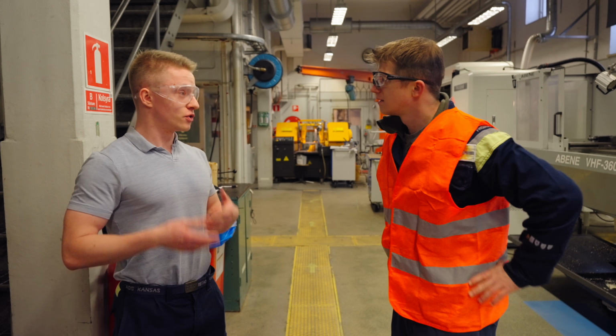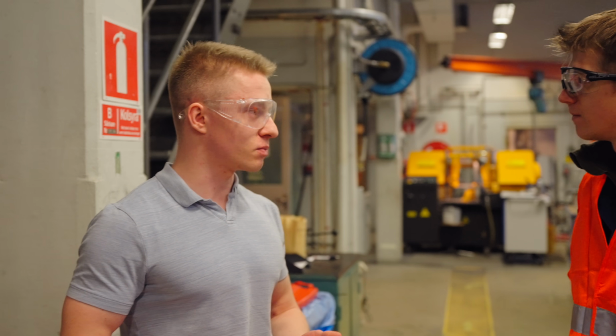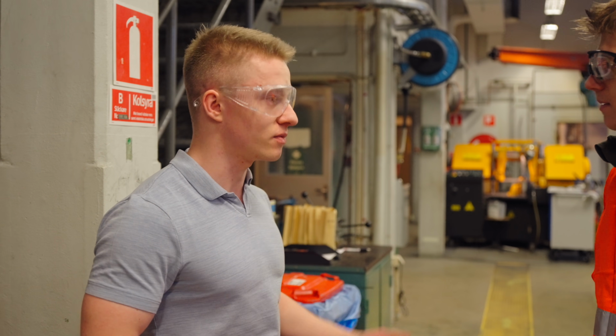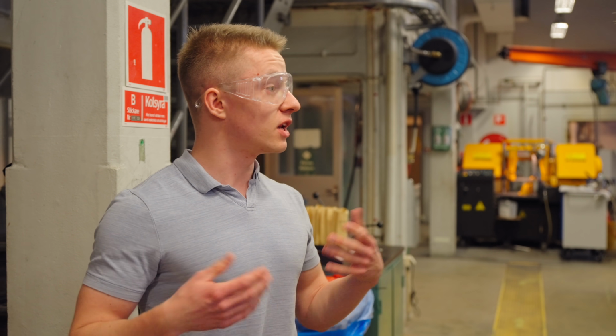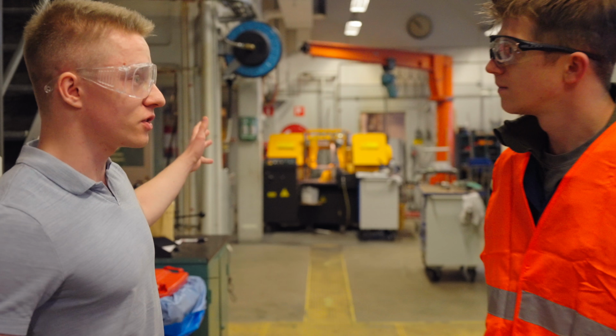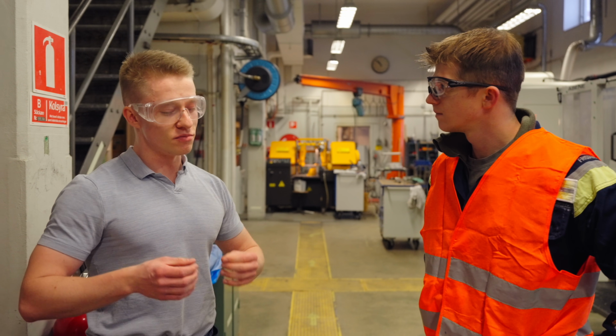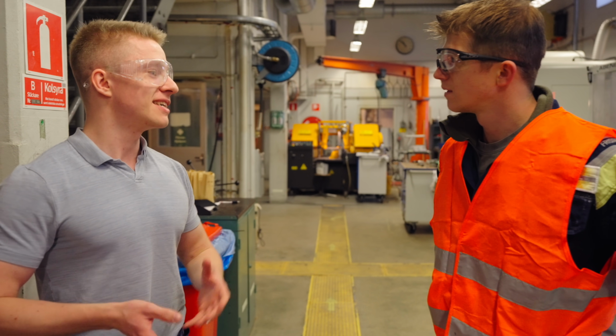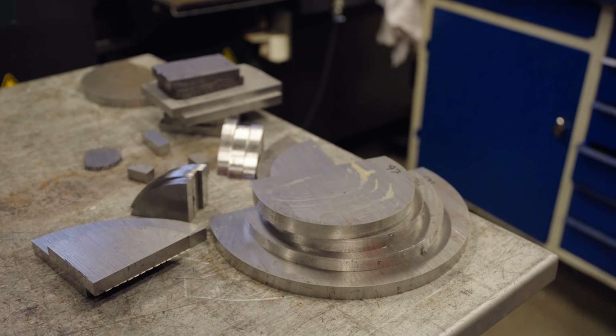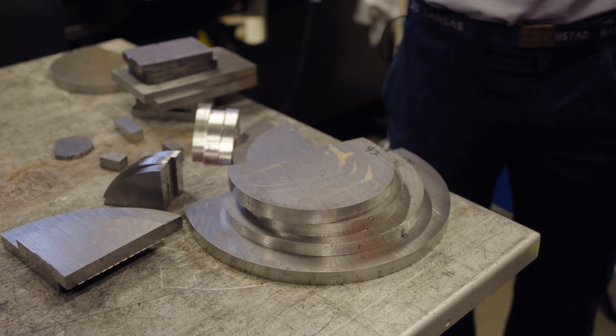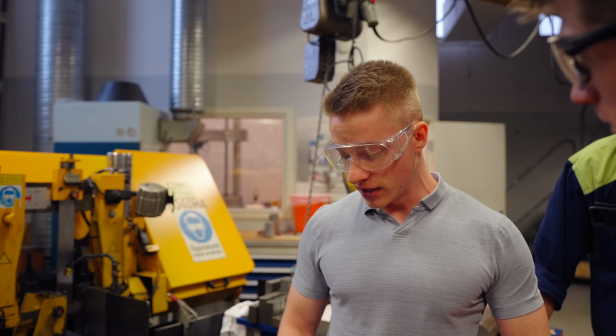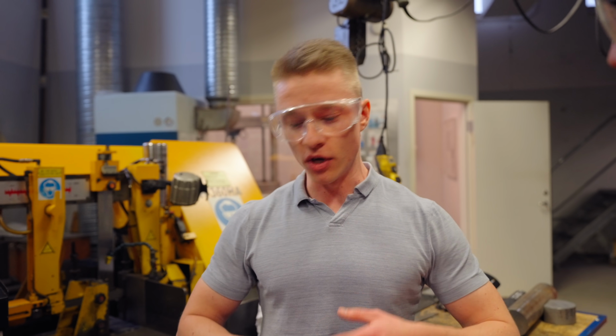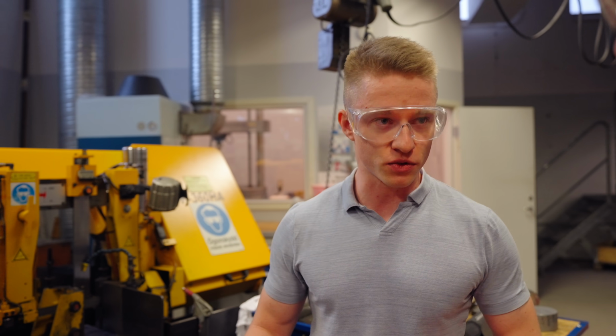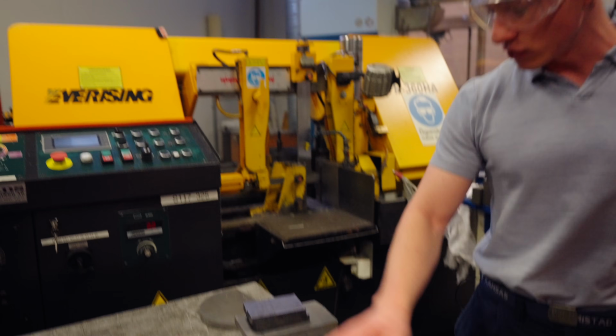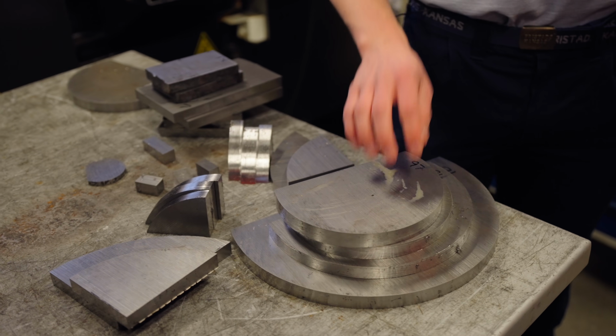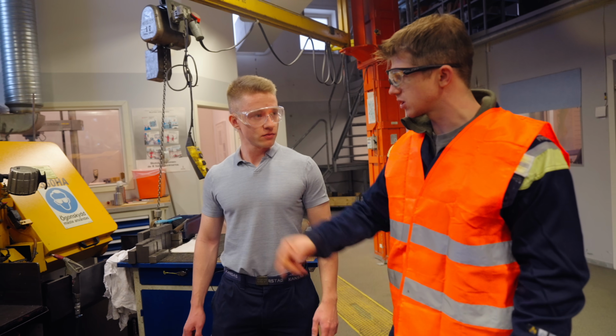Well, more or less you need to for two reasons. One of them is to prepare the samples while we're doing experiments or trials in production. But the second part also is that we're going to do delivery samples. You get pieces from the production unit, then you need to cut them up and be able to analyze them more easily by preparing the samples. Here, for example, this is from production. So we get these kind of slices from the billet line. And this is quite too big to be able to, when you're going to polish the samples to look at the microstructure, etc. So then we need to saw them up into smaller pieces that they're able to be more useful. Okay. Is all the slicing just happening in this saw here mostly?